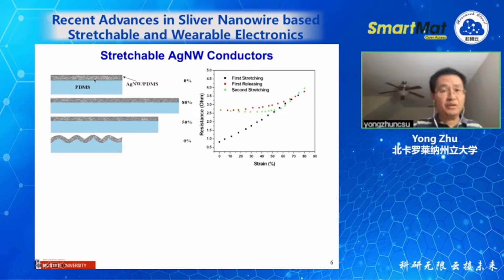Here is the composite structure, nanowire and PDMS. When we stretch, initially at a small strain there will probably be some elastic deformation between the nanowires and between the wires and the matrix. If you stretch further, in this case like 80%, then for sure there's sliding between the nanowires and also between the wires and the matrix. Then when we unload to about 50%, there will be some recovery from the elastic deformation. And when you release it further, as we said, there are millions of nanowires with sliding between them.